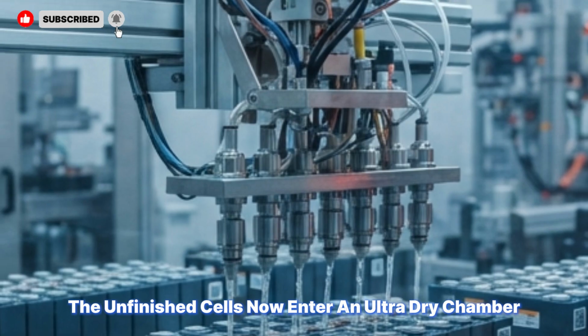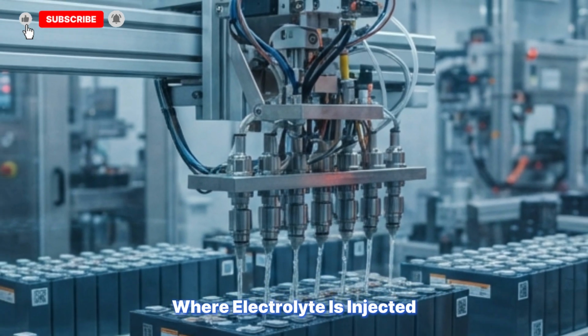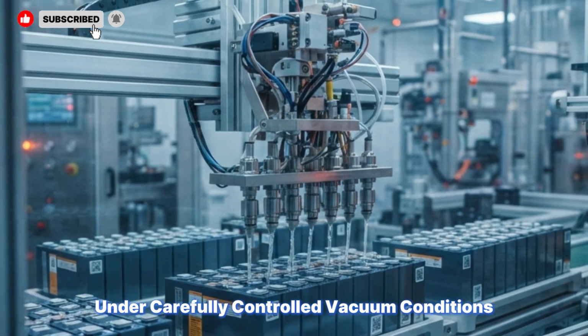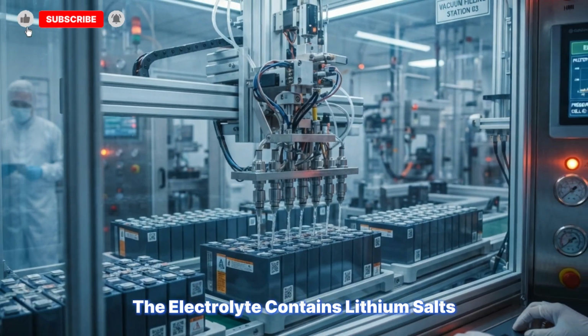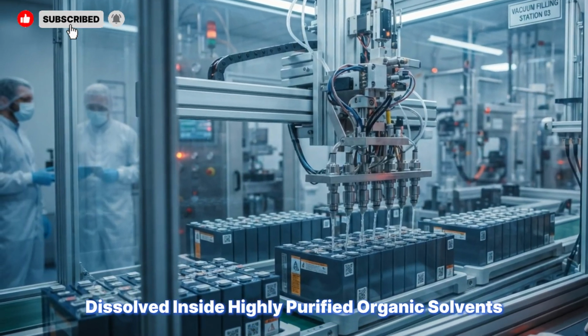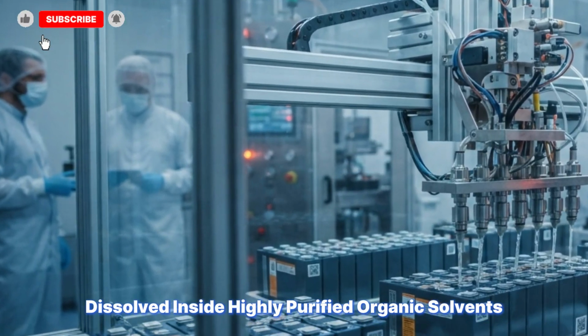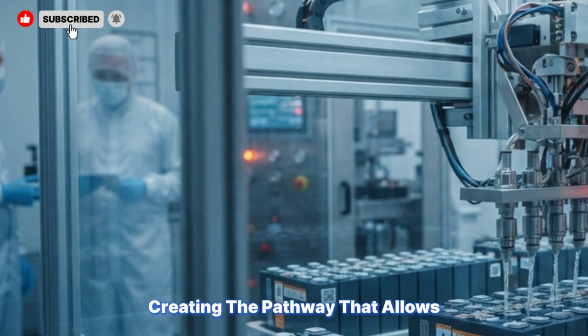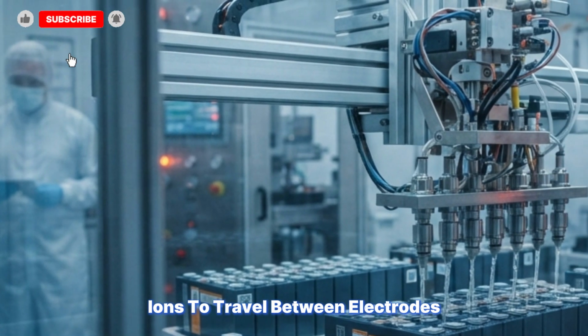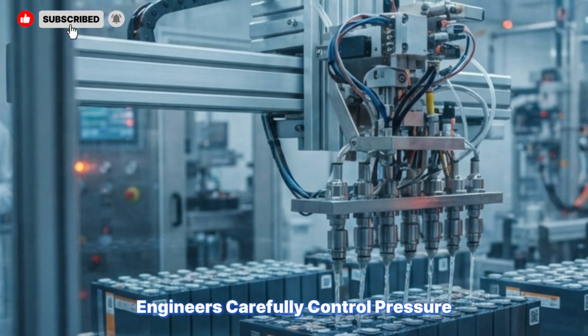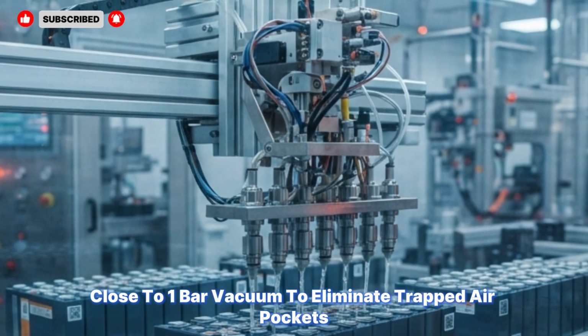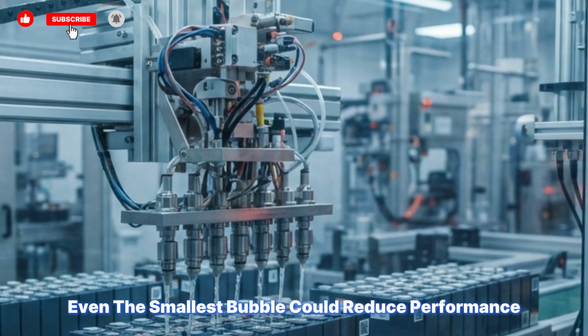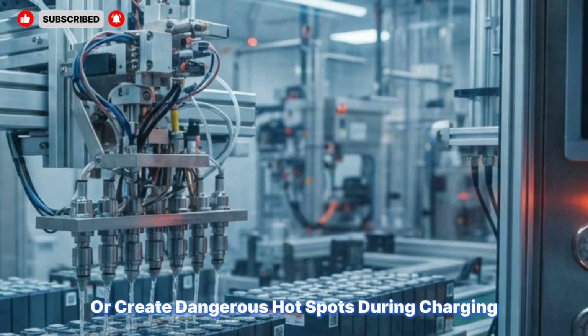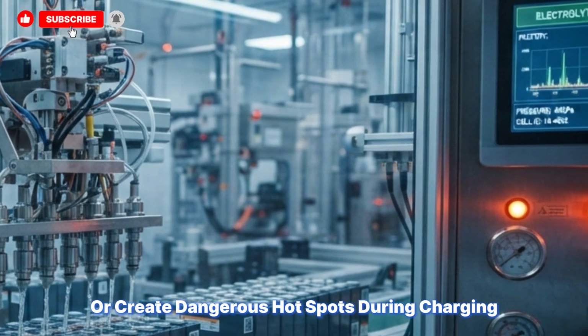The unfinished cells now enter an ultra-dry chamber where electrolyte is injected under carefully controlled vacuum conditions. The electrolyte contains lithium salts dissolved inside highly purified organic solvents, creating the pathway that allows ions to travel between electrodes. Engineers carefully control pressure close to 1 bar vacuum to eliminate trapped air pockets. Even the smallest bubble could reduce performance or create dangerous hot spots during charging.